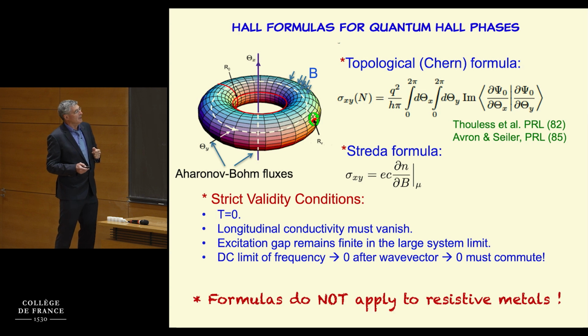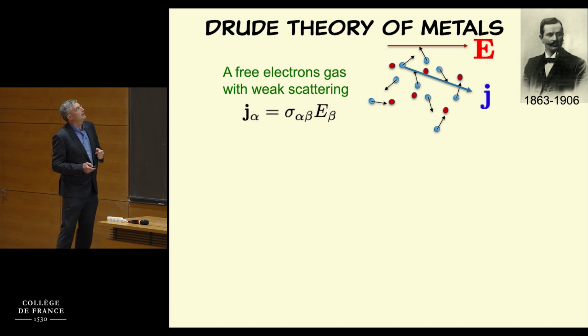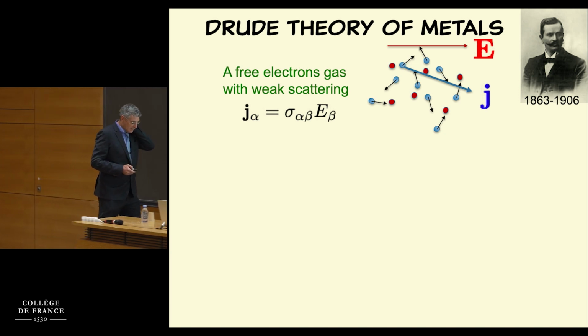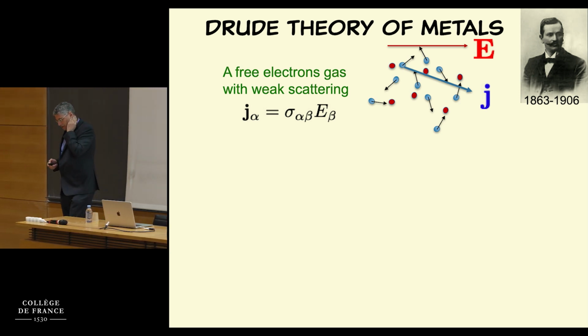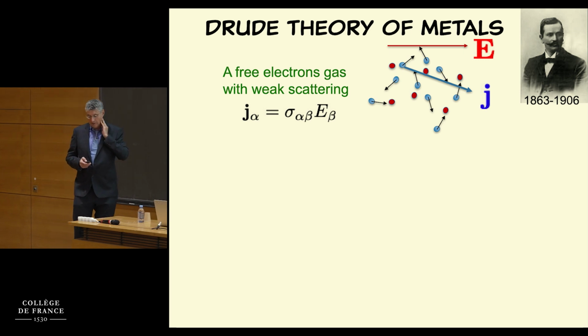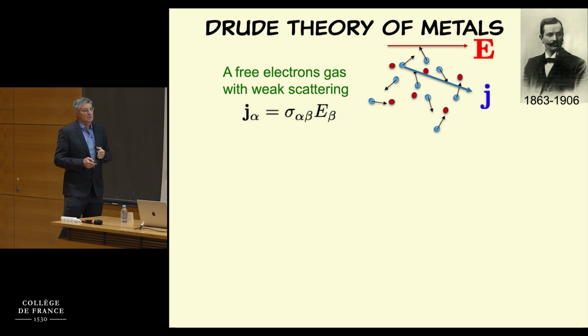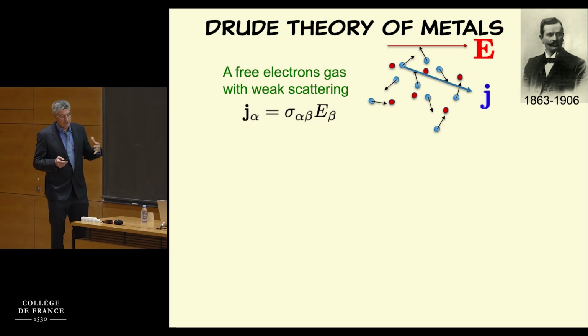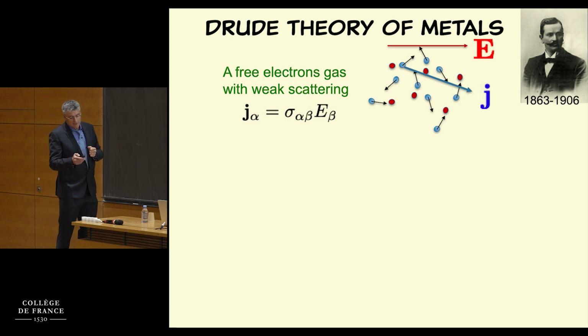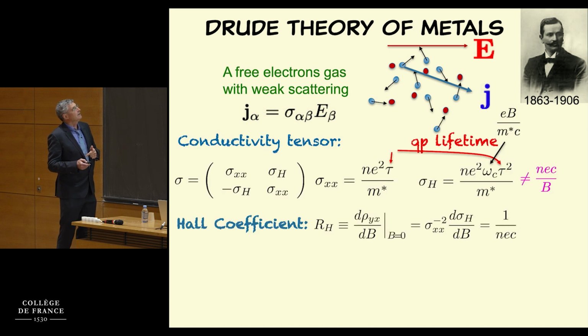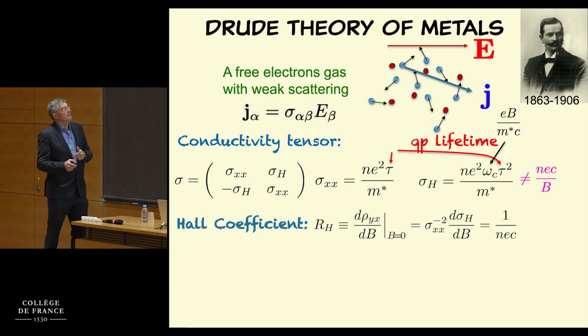So the history is that Drude was a German physicist at the beginning of the 20th century who thought that to think about electrons in metals is really to think about classical gases with no interactions. And classical gases have some scattering time called tau. Because of that scattering, you get both longitudinal and Hall resistivities or conductivities. And this is the tensor that is relevant to the electrical transport. The longitudinal parts and the Hall parts are the diagonal and off-diagonal terms here. The longitudinal part does depend on the lifetime tau between scattering events, the electron density and the effective mass.